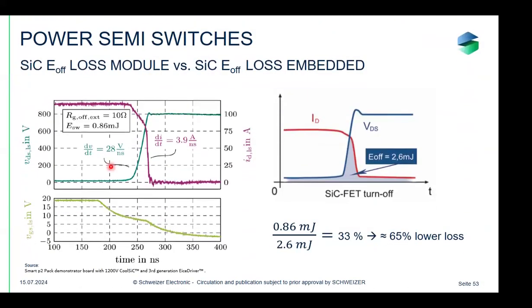But what happens if you take this silicon carbide component into an embedding application? We did that together with Infineon. We made a demonstrator board and did the measurements. And what you can see here is that even though we switched not as fast as we could, only 28 volt per nanosecond with a pretty high gate resistor, the switching off energy was only 0.86 millijoules.